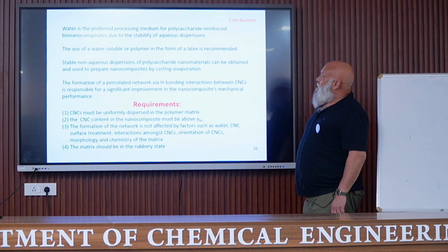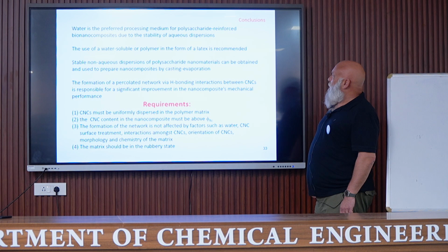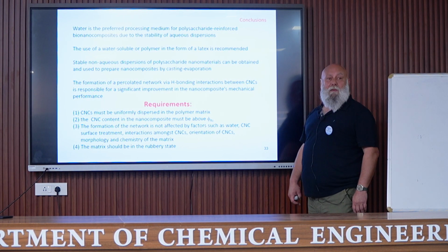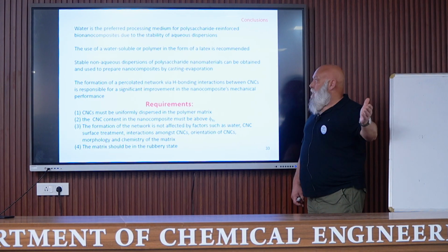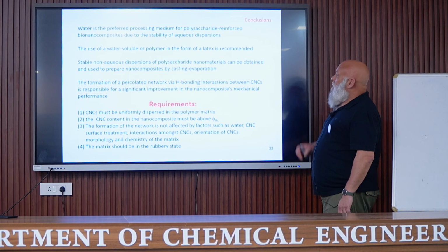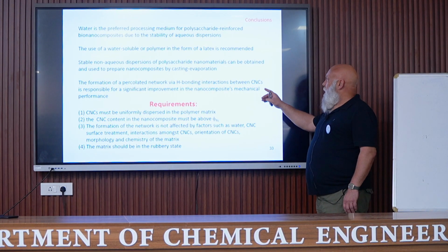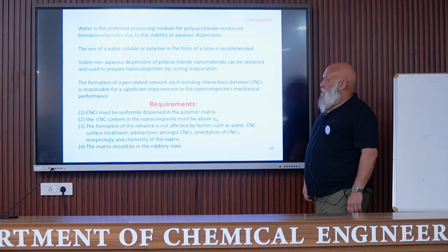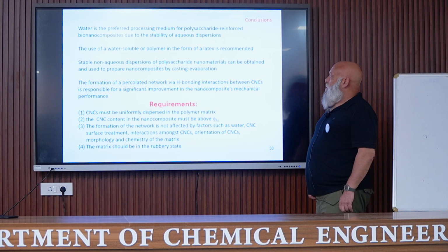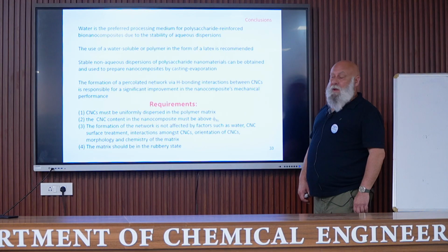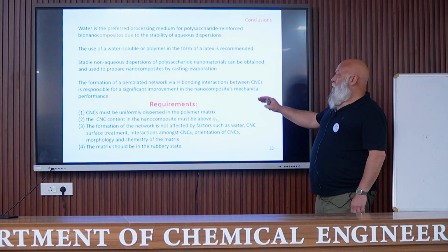Stable non-aqueous dispersions of polysaccharide nanomaterials can be obtained and used to prepare nanocomposites by casting evaporation using another liquid. The formation of a percolated network through hydrogen bonding interaction between the nanoparticles is responsible for a significant improvement in the nanocomposite mechanical performance. Some requirements.